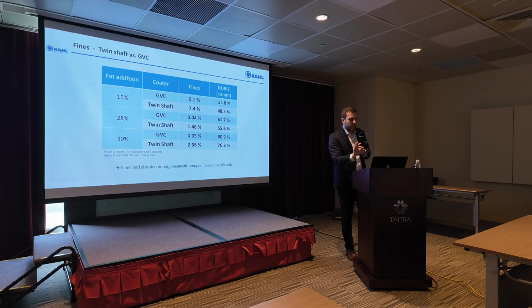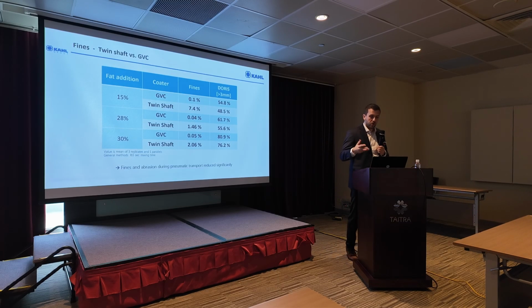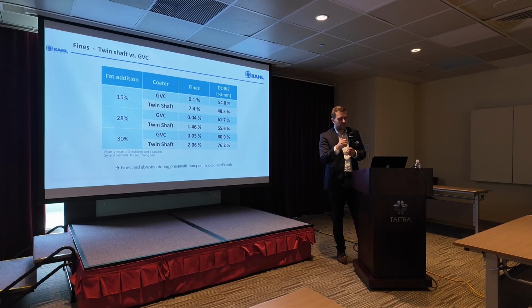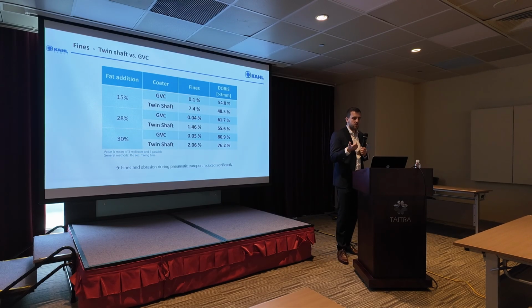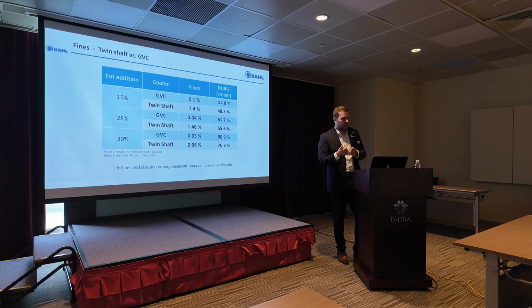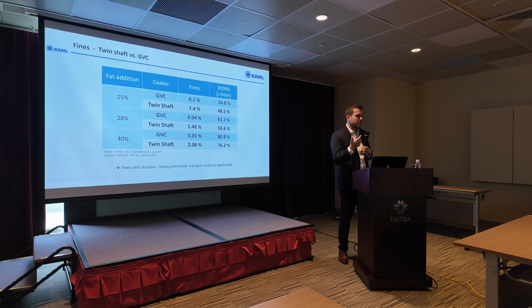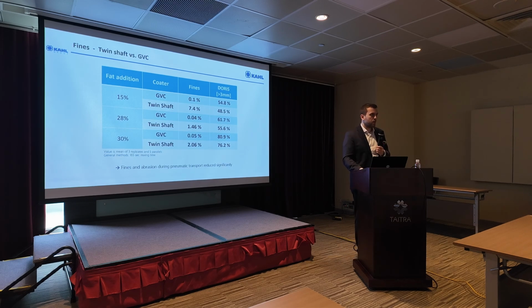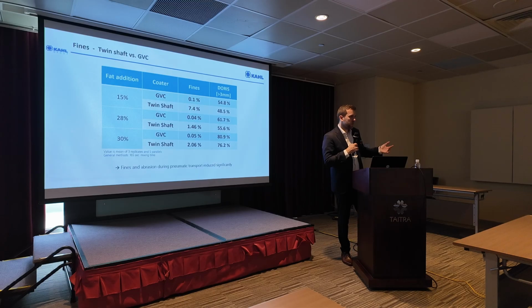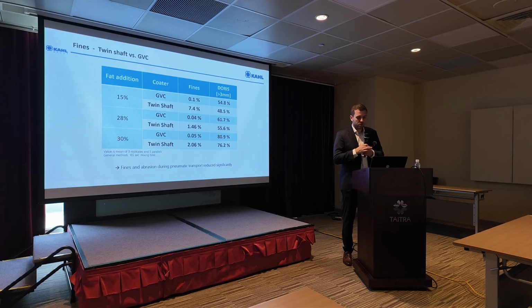And when you now calculate this maybe as a rework, because when you reprocess the product, one has a rule of thumb that reprocessing 1 ton of feed may cost €30 per ton. And now when you think of having to reprocess 7% of fines, this can add up quickly to more than €150,000. So if you can save on dust and fines, you can save on rework, which on one hand is better for your production cost, but also, of course, increases your product quality.